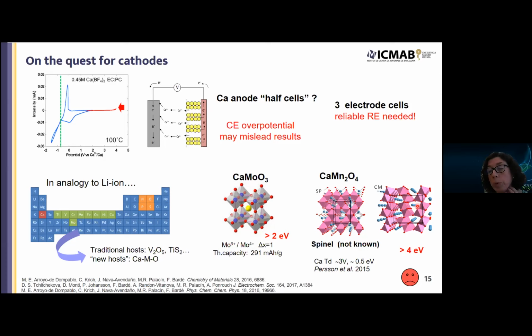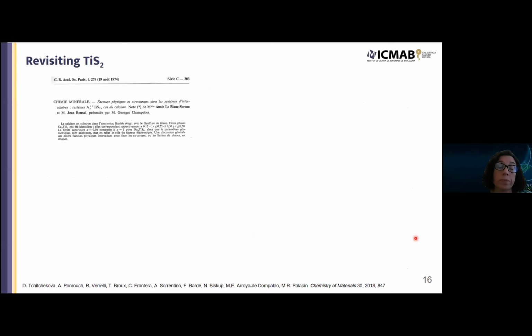But again, when we prepared it and we tried to extract calcium from it, it was not possible. We saw a huge oxidation, which turned out to be only electrolyte oxidation. The X-ray diffraction pattern of this compound did not change. And the calculation of the migration barriers also yielded a very high value.